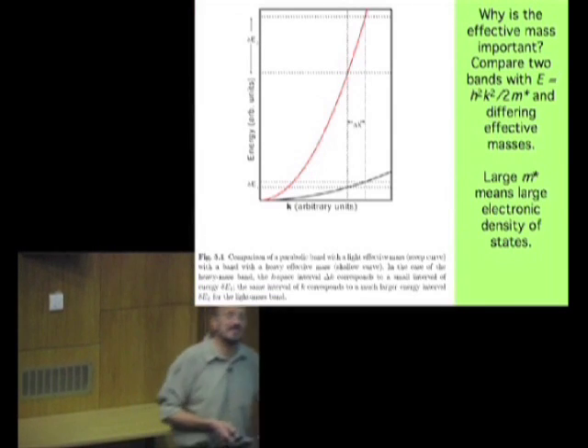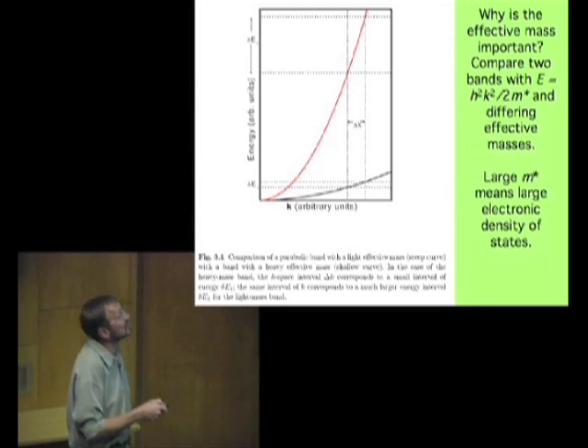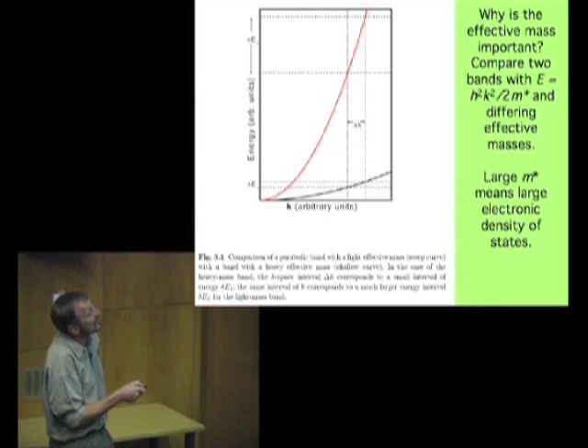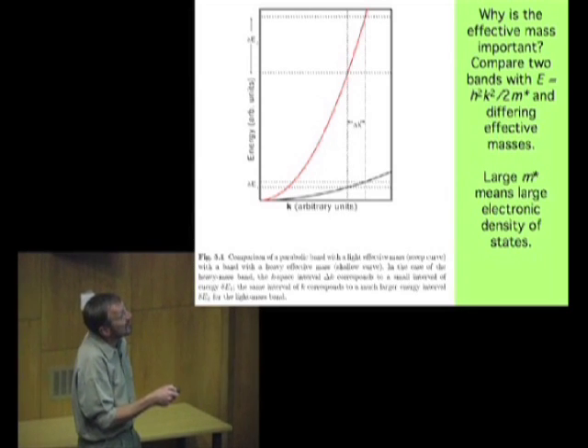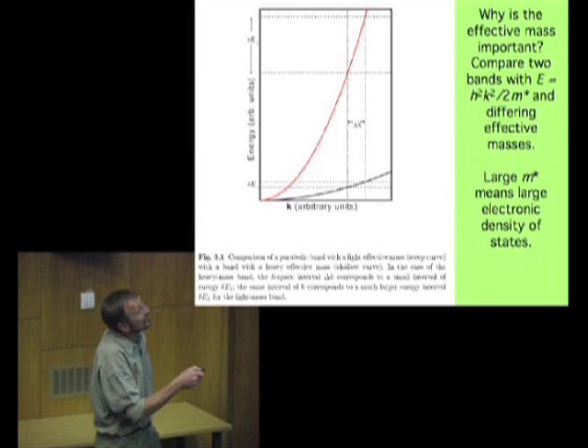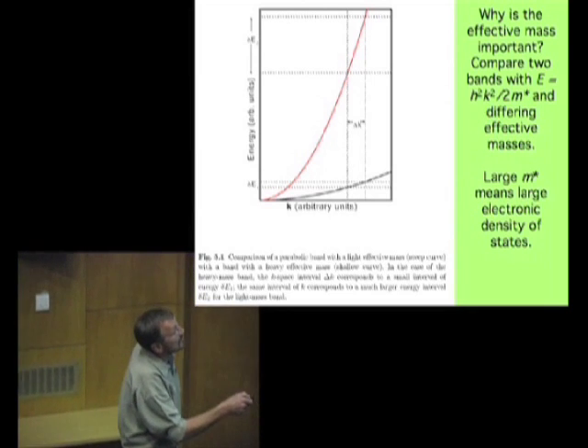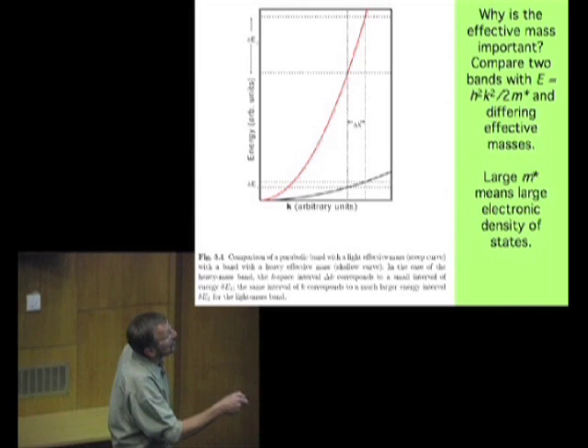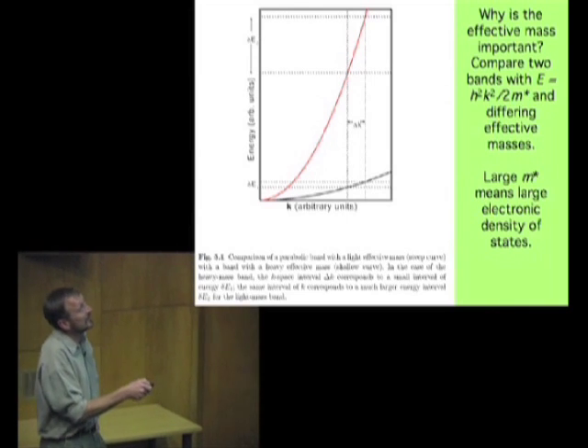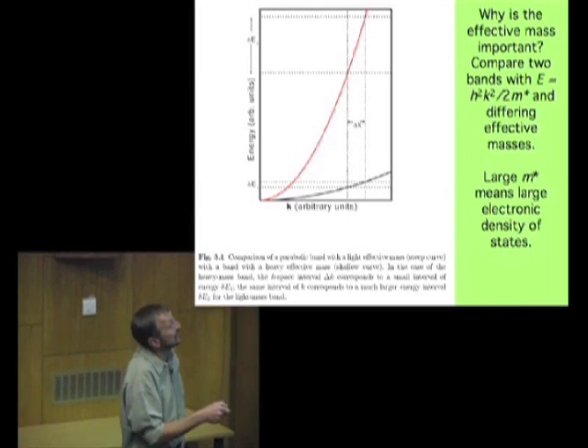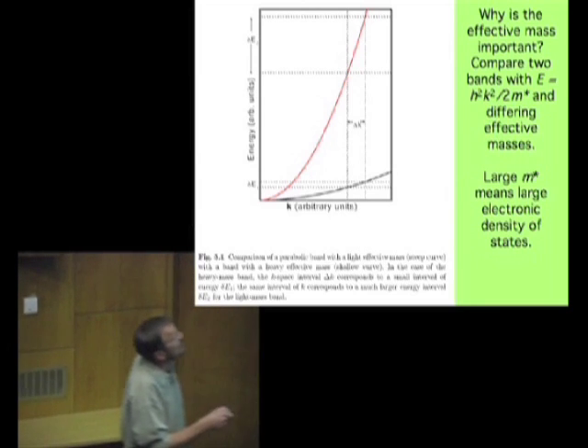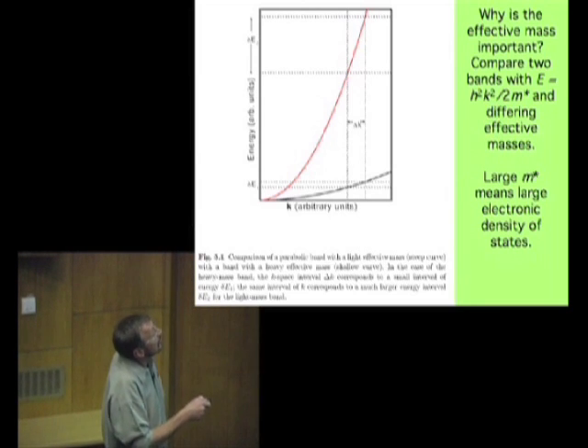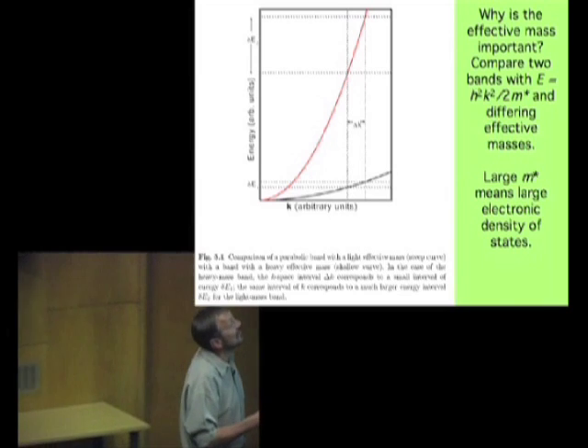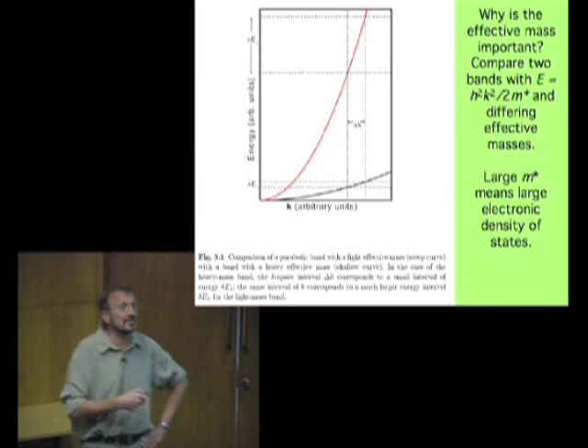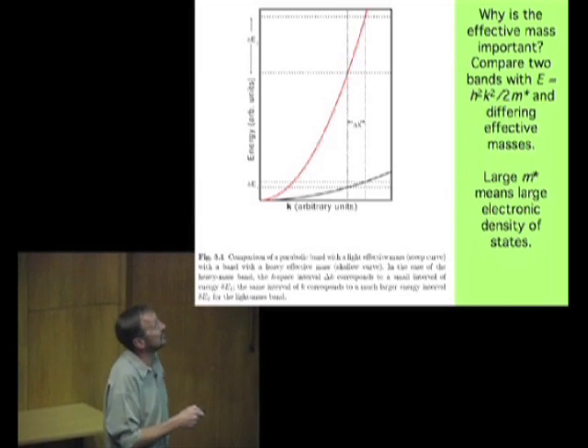Why is the effective mass important? Well, a brief explanation. These are 2 simple bands, one with a heavy effective mass, one with a light effective mass. So there's the simple dispersion relationship. I'm sorry, the bar has fallen off the h-bar in going from Unix to Windows. But what else would you expect? So you know that in K-space, there is a constant density of states, a constant number of states per unit volume of K-space.